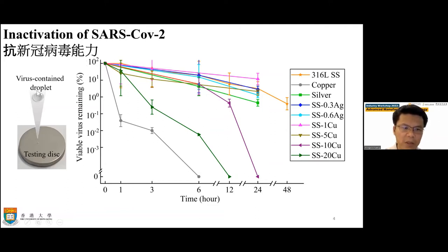We make a droplet. This is a virus-containing droplet, and then we drop it onto the surface, just to simulate the contamination. When you're speaking or coughing, you have a droplet dropping on the surface. We wait for a given period of time, from 1 hour to 48 hours, and then we measure the percentage of virus that is still viable, that means still live virus.